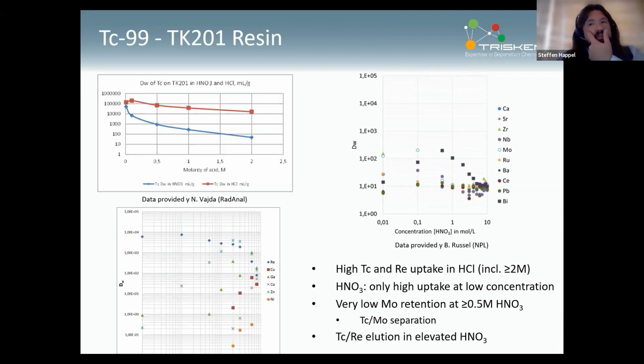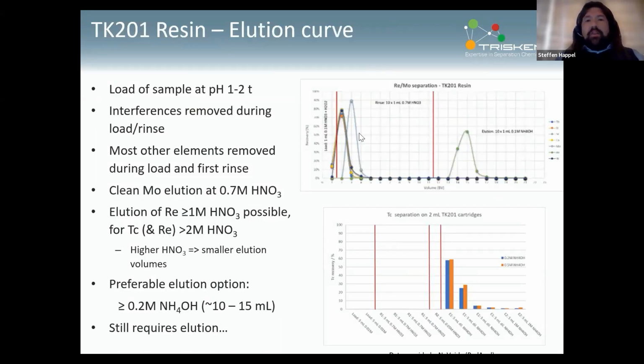Another point that is quite important, maybe even more so for mass spectrometric determination, is that the resin is showing very low selectivity for molybdenum in general, and especially at higher than 0.5 molar nitric acid. The selectivity for molybdenum is extremely low, so that allows for a quite nice separation of technetium from molybdenum. So that's something that we've been testing out. It's basically the wide variety of elements that were tested are removed during load and rinse. That is including molybdenum, which is removed quite sharply.